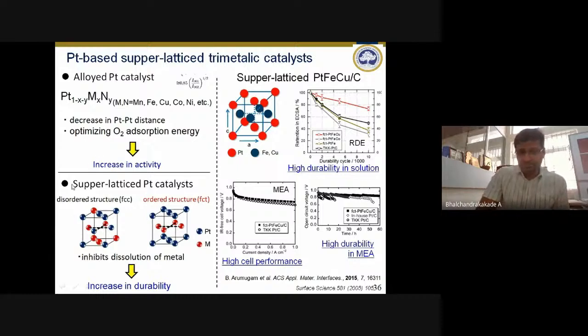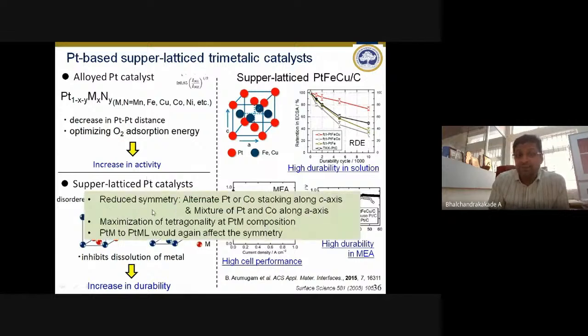And you can see that when we make these superlattice structures, what we are going to do? We can reduce the symmetry. Alternate platinum and cobalt will stack along the C-axis, and a mixture of platinum and cobalt will be along the A-axis. So what is the effect of that? It maximizes the tetragonality of the PtM composition. When we make 50% of the transition metal together with the platinum, then we maximize the tetragonality. So it forms the face-centered tetragonal structures. And definitely when we have PtM and PtML kinds of structures, it will affect the symmetry, and we expect high activity and high stability.